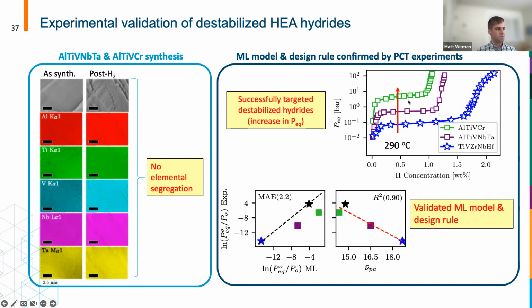So if we plot experiments versus machine learning predictions, again, pretty good correlation between those two. And also, if you look at the experimental or predicted log equilibrium plateau pressures versus this primary design descriptor, again, we get a nice linear correlation. So it's validating the machine learning model and also this first order design rule.